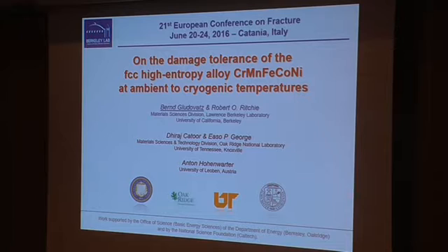After we got these quite exciting and amazing results, we got a little worried that the numbers were maybe a little bit too high, so we decided to get a second measurement, an independent assessment of the fracture toughness that we have measured. For that we used a technique called stereophotogrammetry, which allows us, compared to the global measurements that we have done at the beginning, to very locally measure the crack initiation toughness in the center of the sample at the first physical crack extensions, basically at the intersection of the pre-crack via stretch zone to the overload fracture zone.